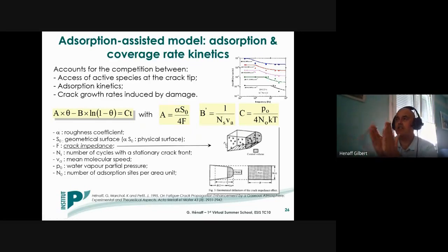the crack will behave as a narrow channel connecting a control volume at the crack tip and the external environment. And due to the very low partial pressure, in that case, the pressure in the control volume can be less than the water vapor pressure prevailing in the environment. And this in particular explains the transition here as the delta K value is increased.